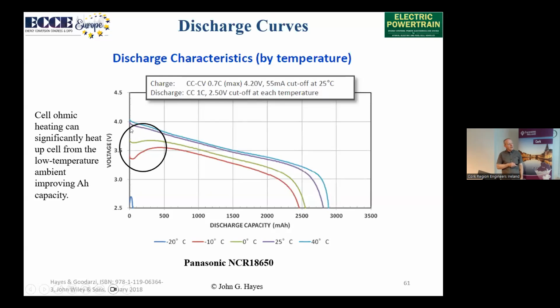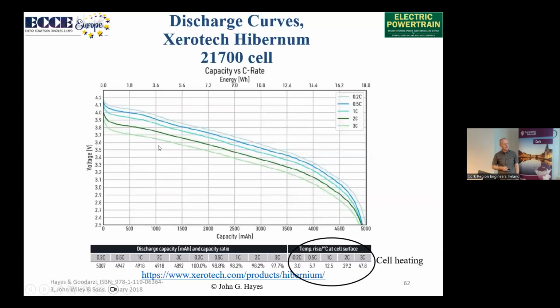the amp hours, the amount of capacity, initially it looks like we're really bad in voltage, but the voltage improves and increases, and then we get more amp hours than we would expect. We didn't get there with this one, but the reason that is happening is this. This is the same from Xerotech again, our folks in Galway.